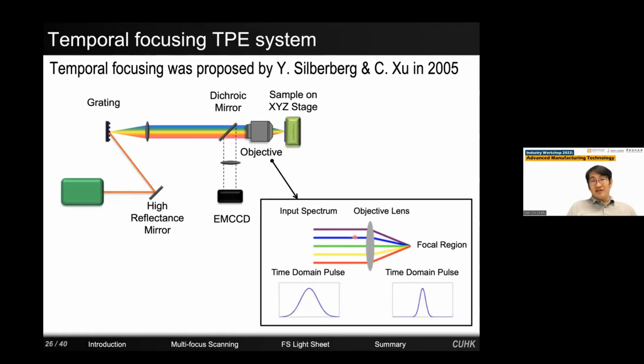In this technique, the so-called temporal focusing technique, we actually exploit and take advantage of the dispersion effect. The femtosecond laser is brought to an optical grating. As a result, the different color spectra are dispersed. When dispersion occurs, the laser peak power is lower and cannot perform multi-photon absorption or excitation. Then all these dispersed spectra are recombined, and only at the focal region do they overlap. As a result, it forms a thin light sheet at the focal region, and right after the focal region, the light becomes dispersed again.